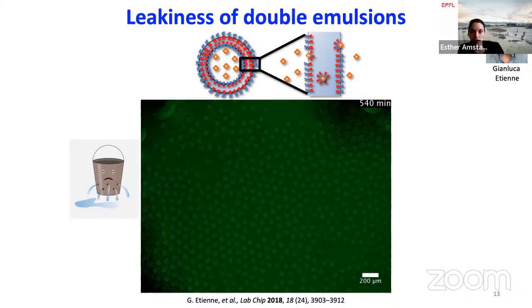And around this time, there was a very nice article published by a colleague from Paris that did a similar study, but on single emulsion aqueous drops in oil, where he claimed that reagents are transported between aqueous drops by the formation of inverse micelles. The surfactants that we use to stabilize these emulsions form inverse micelles and carry the hydrophilic reagents across the oil phase. And so I thought, well, if that happens for single emulsions, that most likely will happen here as well, and that is the reason that everything is released. So how can we suppress that?